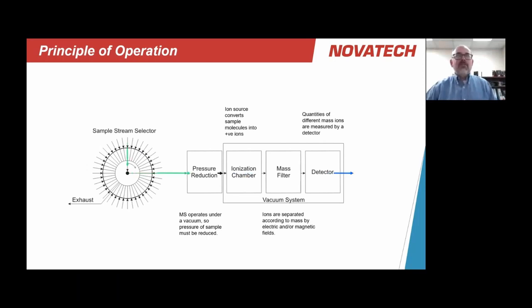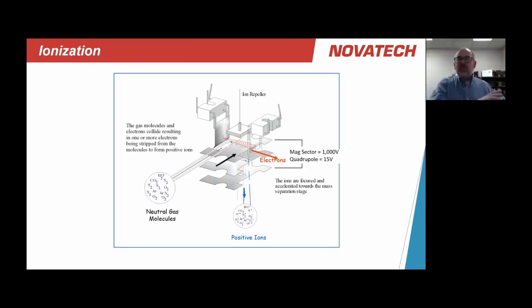So this is what a mass spectrometer looks like. We have some means of bringing the sample to it. And the first thing that happens is pressure reduction. Mass spectrometers operate under very high vacuum, 10 to the minus 5 torr, something along those lines. We then ionize the sample to create positively charged ions. We then separate the sample in the mass filter, which I'll show you in a minute. And then we have the detector that looks at those different components. So that first stage is pressure reduction.